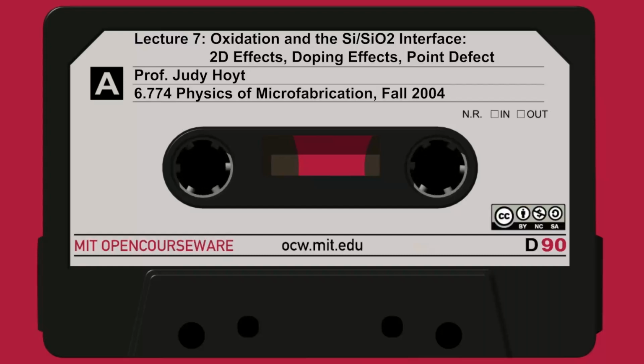So in order to be able to do that, you need to grow the field oxide where you want it, and you don't want field oxide in the active region. Any part of the field oxide that encroaches or pushes its way into the active region means that it's scaling the active region in which you can make your device, so you don't have as much control. You don't get a nice, well-defined active region.